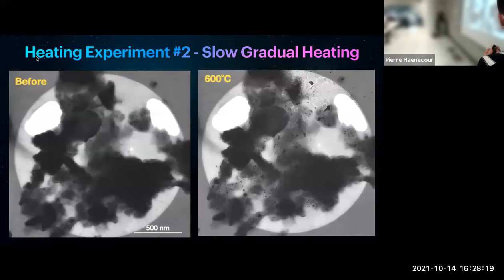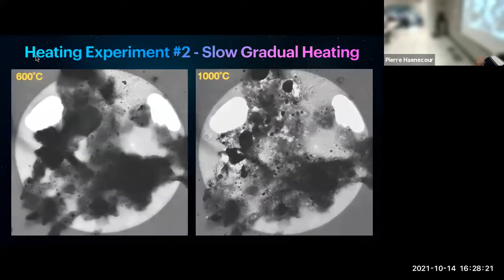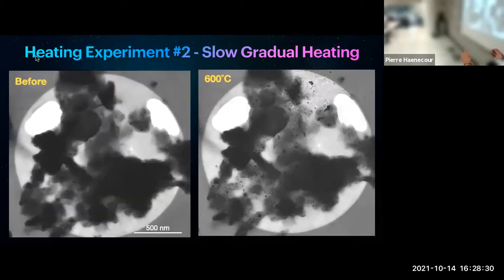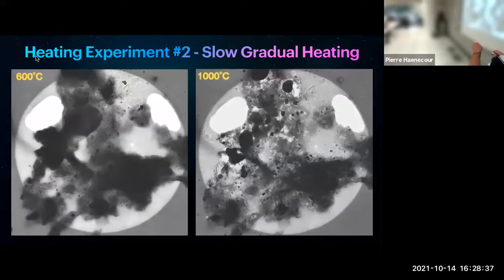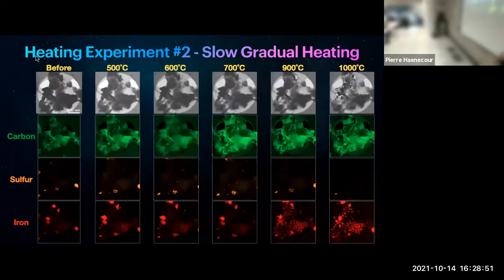Here is another overview, before and at 600 degrees, and then going from 600 degrees to 1,000. Now you can see at 1,000 degrees there are nanoparticles all around, and the carbonaceous matter went from being this dark, diffuse material without any features to a more curve-like texture. You can even see in the carbonaceous matter the trace of where the particles moved around. Those whitest areas are basically particles that swam around in the carbonaceous material.